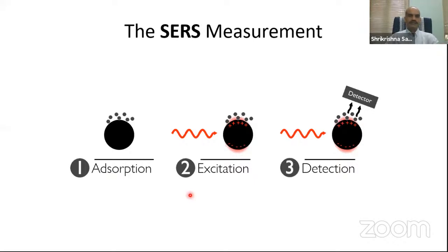So how does it work? This is a very simple way. When I want to do a SERS measurement, I have to have a rough surface, like we have seen in the first paper, but now we have metal nanoparticles of the desired shape and size, where the surface plasmon resonance is close to the incident radiation. We adsorb the molecule we are interested in measuring, then we incident the laser, and there will be excitation of these plasmonic nanoparticles. This enhances the electric field, and the intensity in the Raman spectrum will be enhanced, which we call surface enhanced Raman spectroscopy. This is in this cartoon.